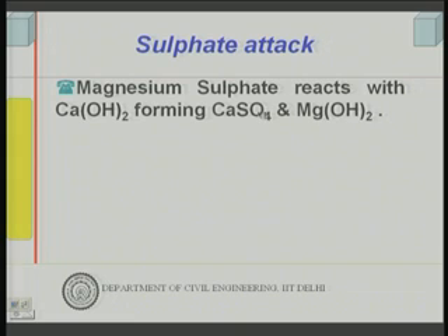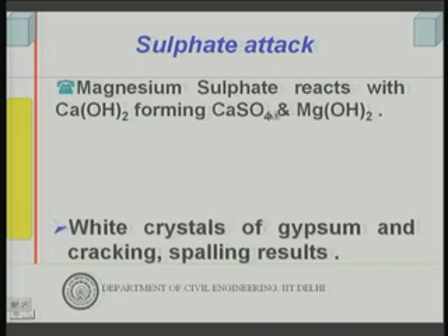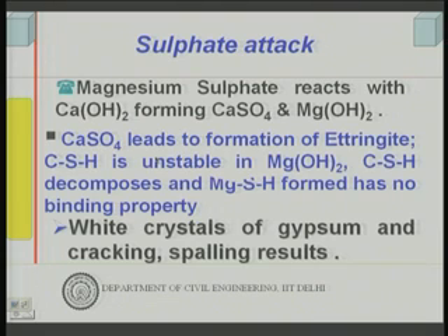and it forms the same gypsum, which will then again form ettringite. Calcium sulphates would lead to formation of ettringite, and the magnesium hydroxide which is present causes some other kind of problem. The CSH gel that we have talked about, that is the cementing material in cement hydrate, is unstable in the environment of magnesium hydroxide. In calcium hydroxide environment it is okay, it is stable, but in magnesium hydroxide environment it is unstable, and it so happens that when you have magnesium sulphate present, it converts all the calcium hydroxide to magnesium hydroxide.